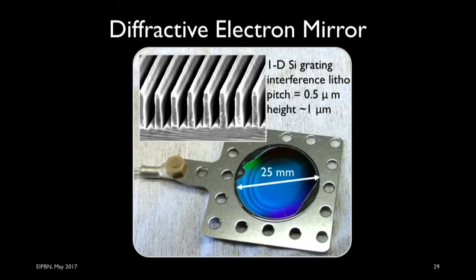This is an SEM image of the cross section of these topographical gratings. They were fabricated on a 1-inch silicon wafer using interference lithography, and in particular using the Lloyd's mirror setup. The pitch of this diffraction grating is 500 nanometers, and the height of these walls is approximately 1 micron.